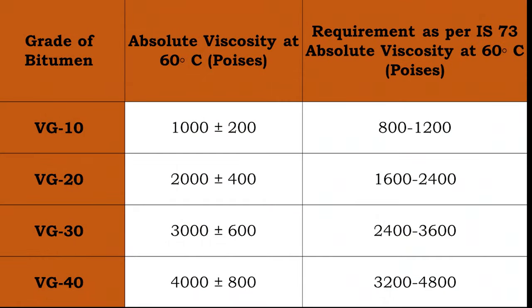Viscosity grading of paving bitumen is based on viscosity measurement at 60 degrees centigrade. This temperature was selected as the maximum bituminous pavement surface temperature during summer. We measure the time it takes for a fixed volume of asphalt to be drawn up through a capillary tube by means of vacuum.